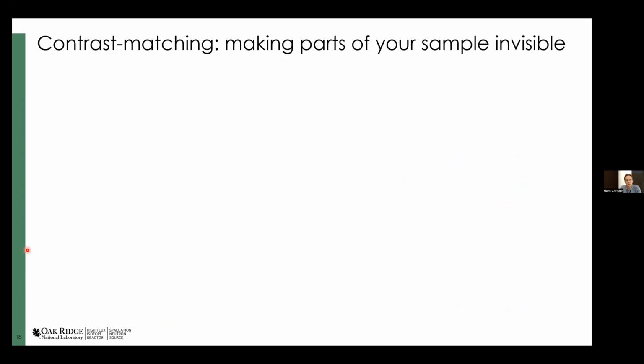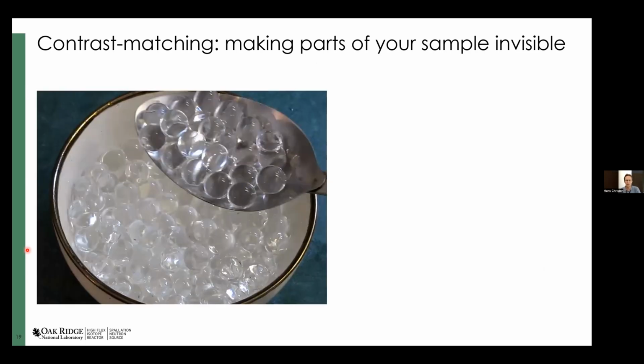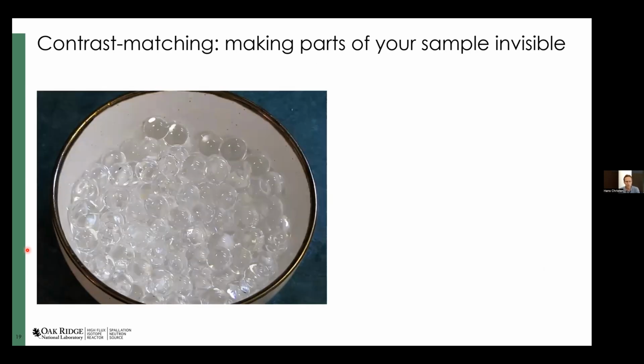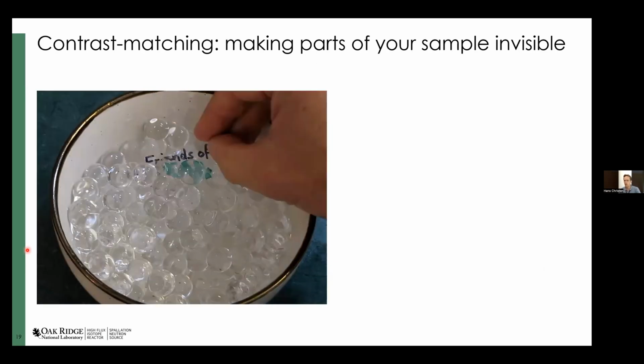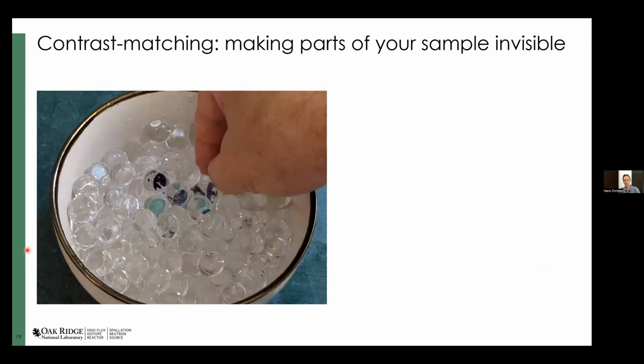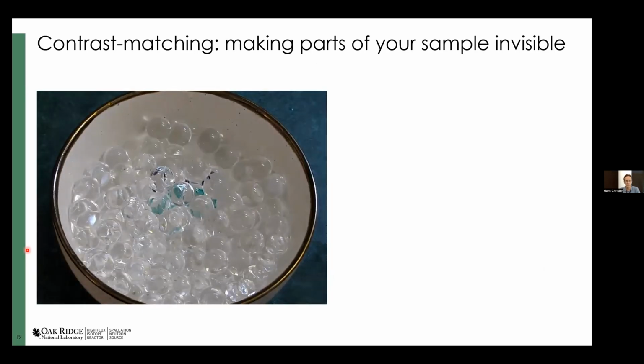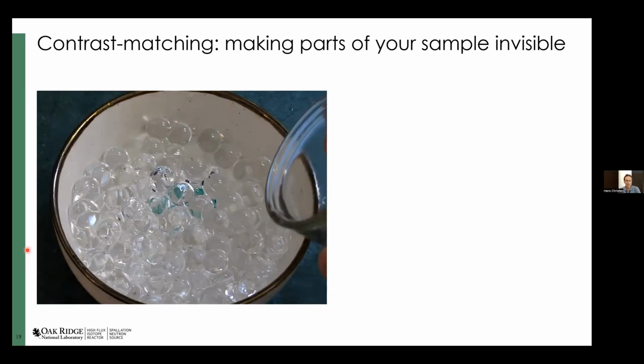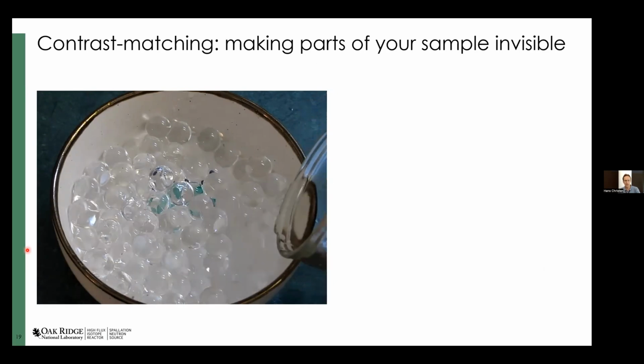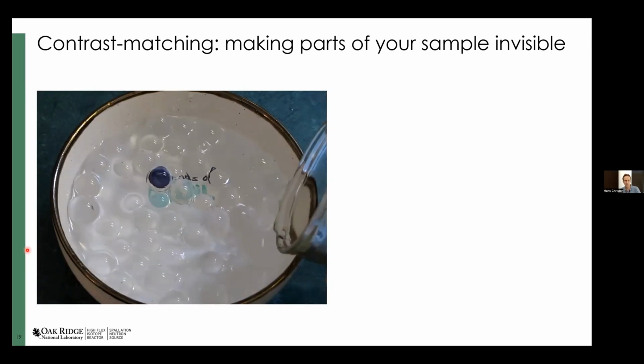The fact that neutrons are sensitive differently to different isotopes, hydrogen and deuterium in particular, makes it possible to do what we call contrast matching. And that's a method to make parts of your sample invisible. So I'm giving you an illustration here of, imagine these polyacrylate beads, and you're looking for some information within those beads. That would be impossible to see until you add something to this environment that essentially makes the beads invisible.